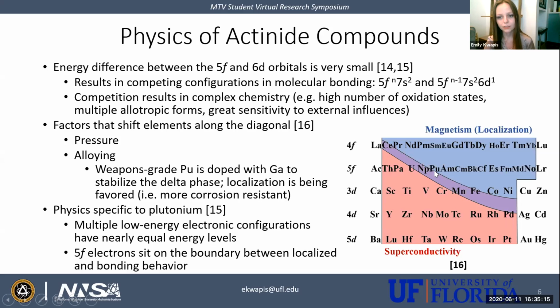So what's special about plutonium is that plutonium lies on this transition between localization and delocalization, or superconductivity in this figure. When you're in the localization region, bonding isn't favored, while when you move into the delocalization or superconductivity region, bonding is favored. Since plutonium is on this transition, it can go either way. When you dope plutonium with gallium, such as for weapons grade plutonium, you're pushing plutonium to the right in this figure into the localization region, and that causes the alloy to become less reactive and more corrosion resistant. Since cerium falls between uranium and plutonium along this diagonal, I would expect the physical chemical properties of cerium to be somewhere in between uranium and plutonium.